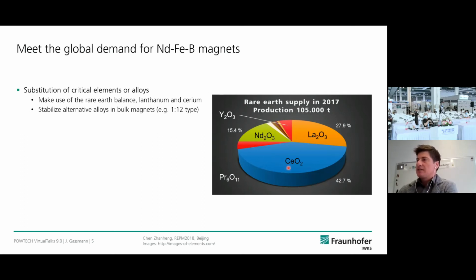This is the natural rare earth basket of elements, and the most promising element is neodymium, in neodymium oxide. About 15% of the rare earth ores is neodymium, and the mining is driven by this element. However, during mining of 1 kilogram of neodymium, also 1.5 kilograms of lanthanum and about 2.5 kilograms of cerium are mined, and these materials can also be used in permanent magnets. So there is research going on in this field for using the natural balance of rare earth elements for producing magnets, since these materials are mined more than is needed at the moment. So they are more or less dumped after mining.